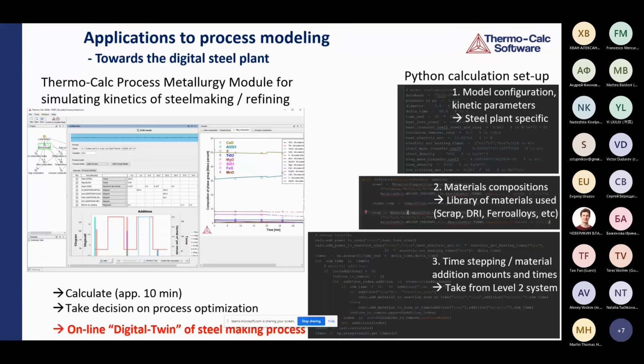Another example could be application to process modeling. So that's to get towards the digital steel plant. And here we're using the process metallurgy module inside Thermo-Calc for simulating kinetics of steelmaking and refining. It was done using the graphical interface, but you can also use it in Python to set up a calculation where you have a model configuration of kinetic parameters, and you can use the steel plant specific data. You have probably a different kind of materials composition for that kind of steel process. Then you can do time stepping, material addition amount, and connect that to the level 2 system from the steel plant. And then you can take decisions on the process optimization steps that are necessary. So it's a kind of an online digital twin of the steelmaking process.